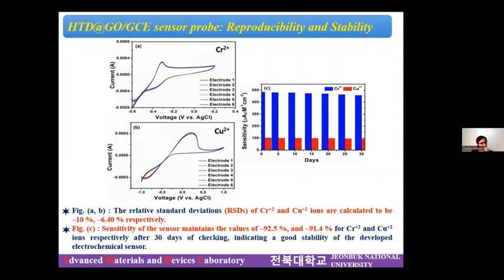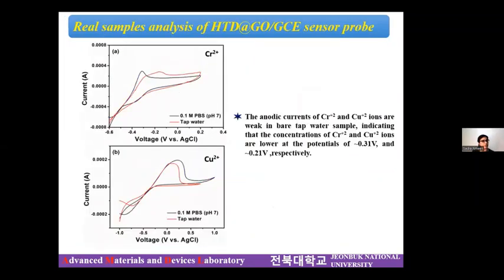That means that our synthesized electrode is reproducible, and for the purpose of stability, we performed this sensing experiment for 30 consecutive days, and it didn't show any major deterioration in the electrode surface. That means our synthesized chemical sensor is both reproducible as well as stable. And finally, we wanted to check real samples. Here we have taken tap water apart from the PBS solution, that is phosphate buffer solution. We found that the intensity in the case of tap water is somewhat lower, which might be due to the lower concentration of chromium and copper ions in the tap water.